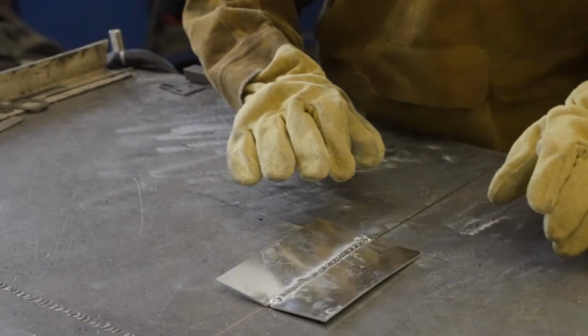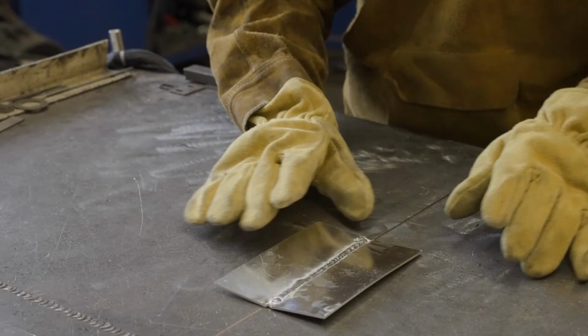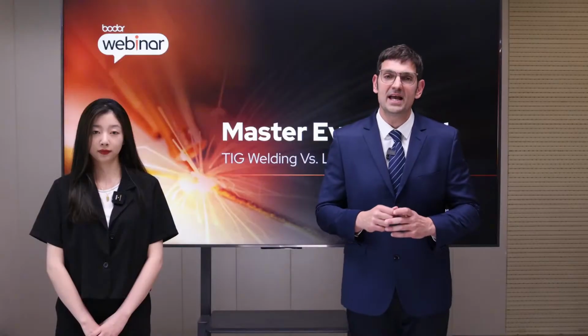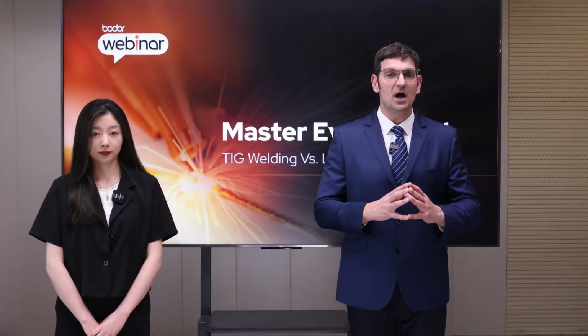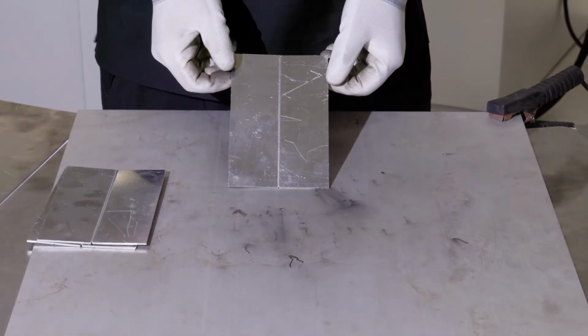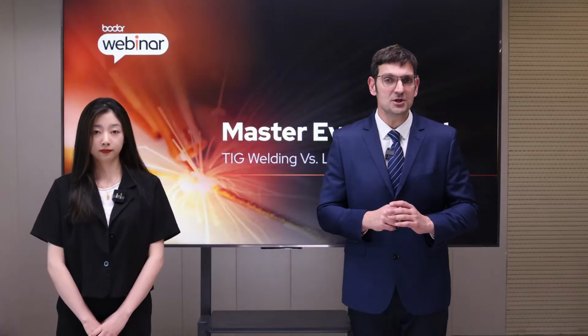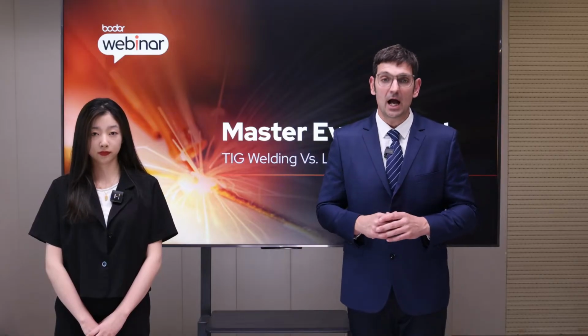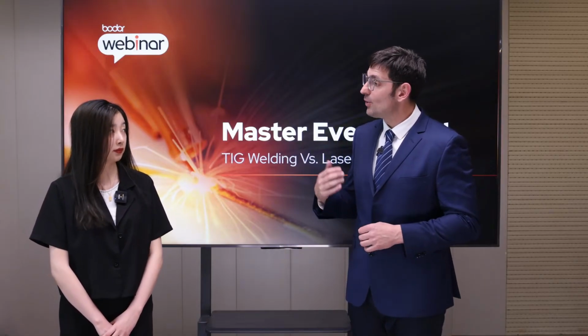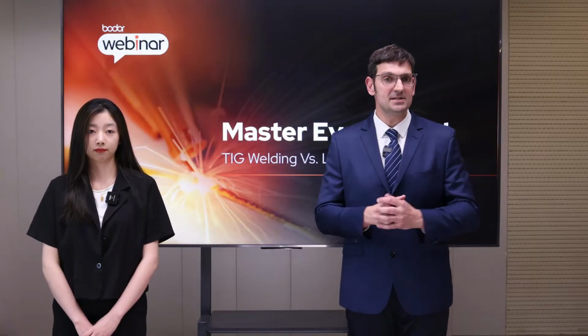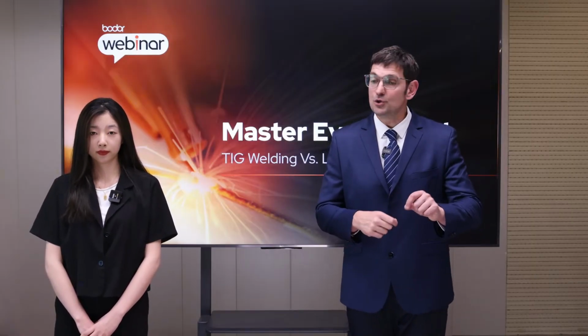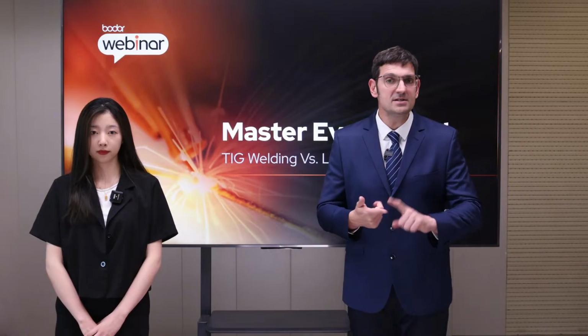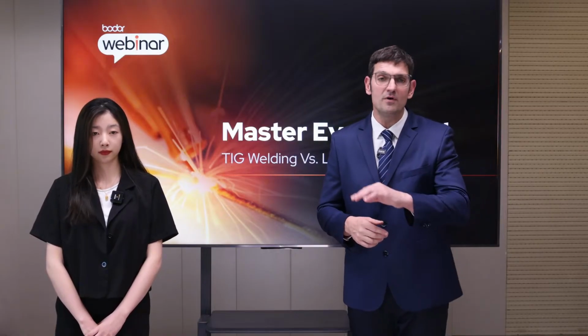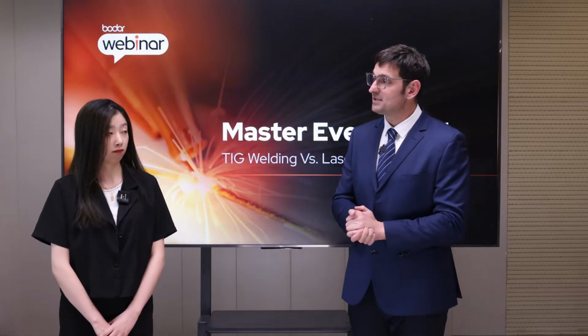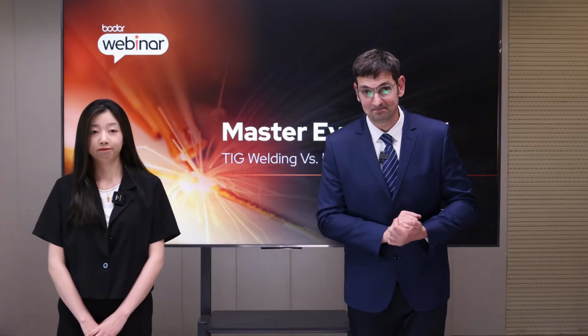or edge burn. On the TIG welded piece, you can feel and even see some slight warping along the edges. On the laser welded side, the base material stays much more stable. There's no visible deformation and the edges remain flat, a huge plus for maintaining dimensional accuracy. In most cases, the result is so perfect, you can skip post-processing. No grinding, no sanding, just weld and move on. It's a kind of finish that not only looks professional, but also saves a ton of time and effort.